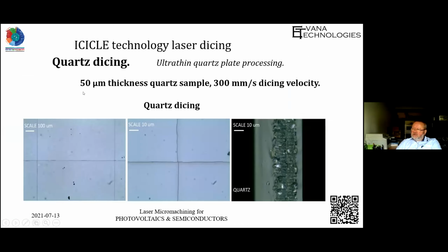We also have some experiments with ultra thin quartz dicing, and we had good results for quartz dicing at 50 micrometers thickness with 300 millimeters per second velocity. You can see the surface view. It means that you have no damage by the laser, you just get a crack from inside, and this is the cross section of the material.